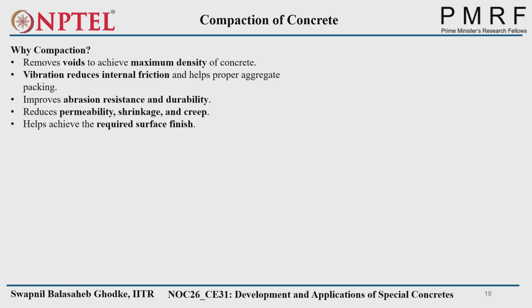Why do we have to remove voids? To achieve the maximum density of the concrete. Vibration reduces internal friction and helps proper aggregate packing. So vibration is one of the ways to compact the concrete. If you provide vibration, it will help reduce the internal friction between the aggregates, and they will go into place wherever space is available and reduce the voids in the concrete matrix. Further, it improves abrasion resistance and durability.